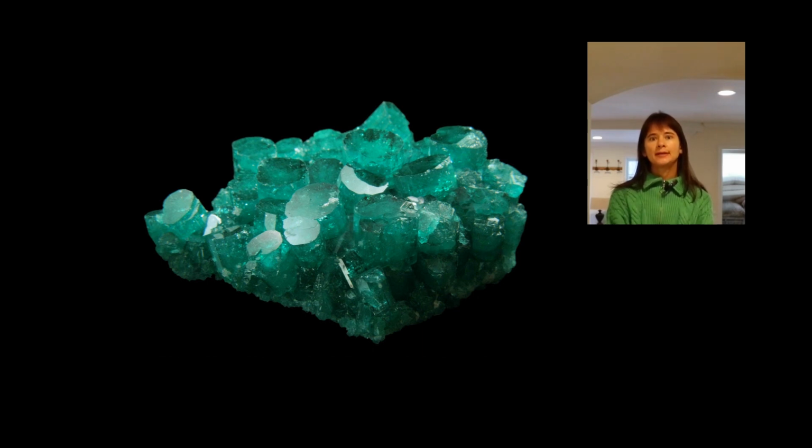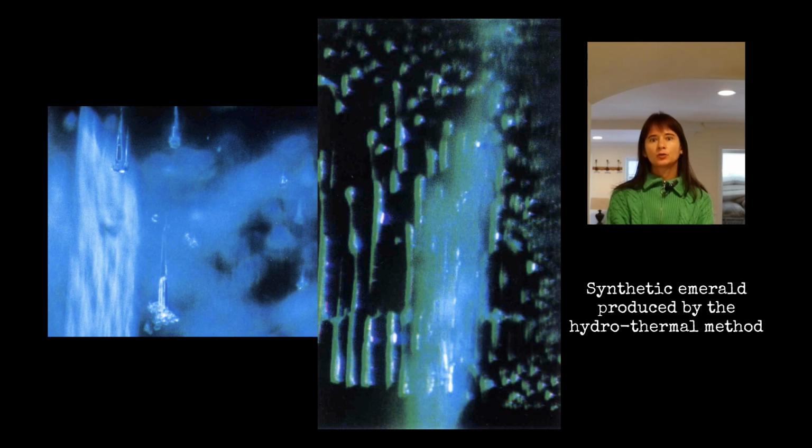Spontaneous nucleation may be inhibited by installing a slice of beryl as a pattern for the grown crystal, which continuously grows as long as all the dissolved material is attracted to the beryl plate and forms one single crystal. This is an optimal result for a crystal to be used as a gem. Through this process, the hydrothermal method differs sharply from the environment in which natural emeralds are formed, notably by the lack of water.